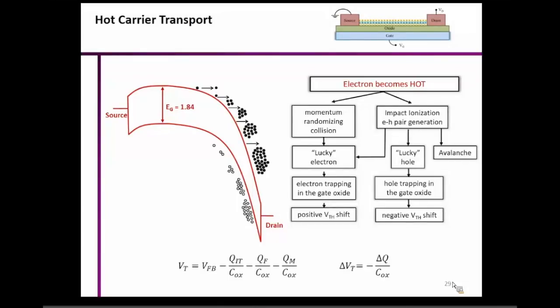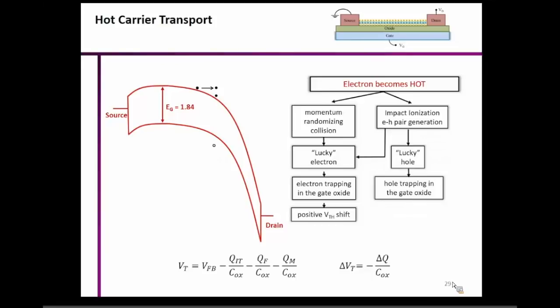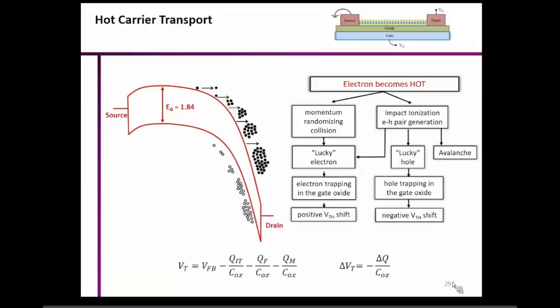an avalanche process. And to a certain extent, if I go back to the last slide, I don't know whether I have it in the next slide, you can clearly see that when I'm in the off state, I'm injecting holes because I have a threshold shift in the negative direction, and when in the on state, I'm getting more of an electron injection. And these kinds of studies are very important to understand the reliability of these 2D materials, how far you can stretch or bias these 2D materials. Okay? And this could be used again for harsh kinds of conditioning of these devices.